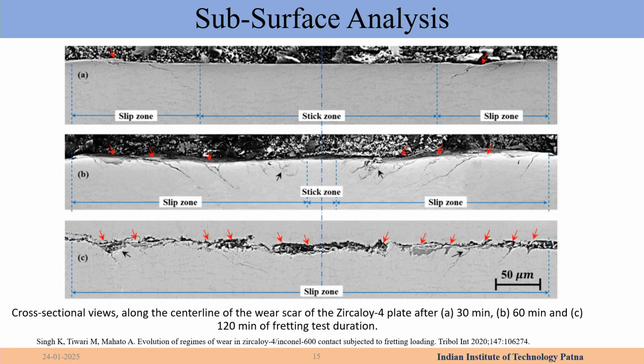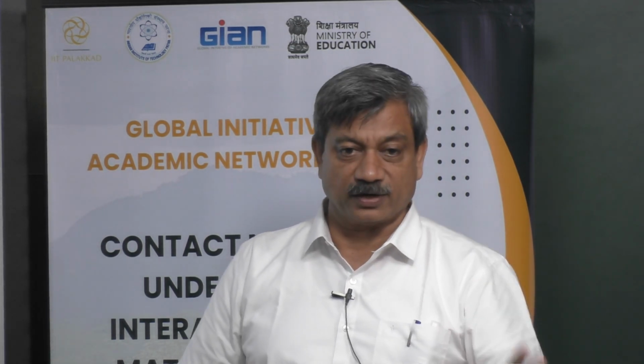And these are the cracks in the SEM. You can see what's happening after 30 minutes, 60 minutes and 120 minutes. You can see the cracks and their size increasing. This is the slip zone in between, 50 microns. I should tell you the contact area, if we just calculate, was about 240 microns in diameter, 120 microns. Our amplitude peak to peak maximum is 45 microns, so it is much smaller than the contact area which we've estimated from Hertzian contact theory.